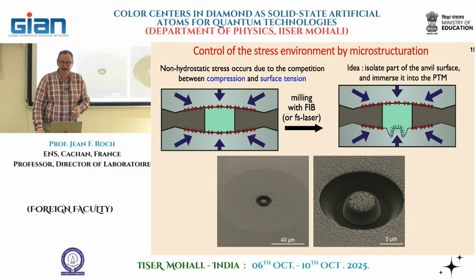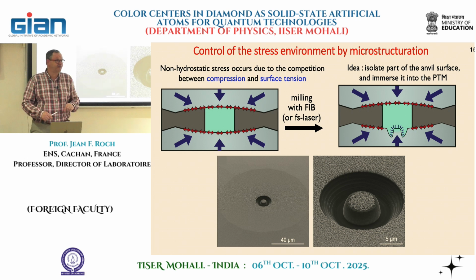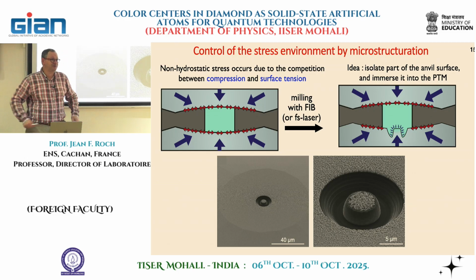So this is a pillar. It's a stiff pillar. It's wider, a few micrometers, and just a thickness of 1 to 2 micrometers, rather stiff, but enough, we thought, and we did some calculation about that. Also, it's quite difficult, but nevertheless, we convinced ourselves that the geometry could be efficient for doing that.